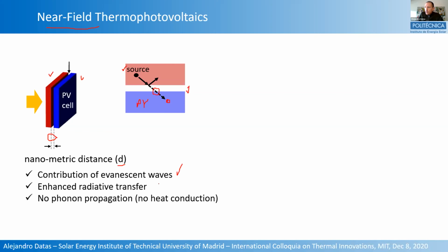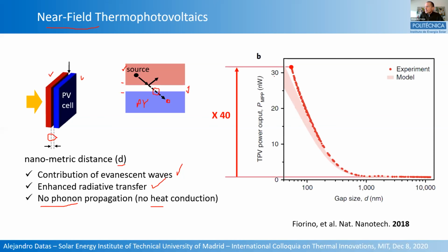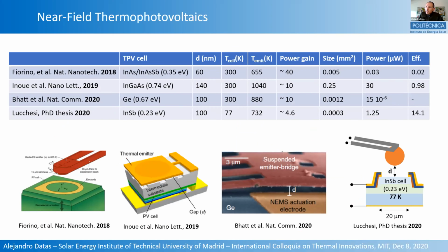So you have a contribution of evanescent waves, which enhance the radiative transfer. And very importantly, you don't have any phonon propagation. So there is no heat conduction because the hot side and the cold side are interrupted by a nanoscale vacuum gap. So only photons can cross this gap. And well, very recently, there have been very encouraging results, as for instance in this publication by Fiorino in 2018, where you can see that when you reduce the gap distance, then you have a drastic increase in the power density, in the power output of the device, in this case up to 40 times when you reach distances as low as 100 nanometers.